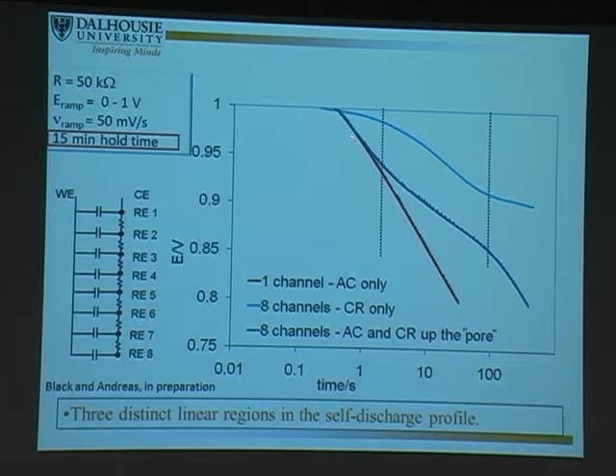where we have this region where our self-discharge profile is matching the activation control. And that's where the charge redistribution has not yet started. So the charge hasn't yet started moving deeper into this pore. So the activation control process is dominating the electrochemistry at this point. Then the charge starts moving down into the pore, and we see that as a change in slope.